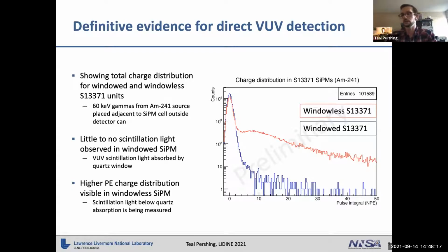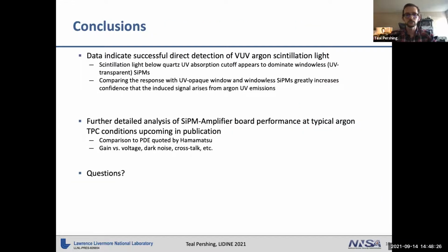So we're pretty convinced that we're seeing VUV scintillation light from gamma scattering inside of the liquid argon in the test cell. The data seem to indicate that we're getting our first, for our group, detection of this argon scintillation light. The plan from here is to do a further detailed analysis, where we'd like to calculate the photon detection efficiency and compare that to the quoted values for Hamamatsu, and then go further and calculate the general characteristics of our SiPM amplifiers: gain versus voltage, dark noise, crosstalk, and so on. So I think I'll stop there and I'll take questions.